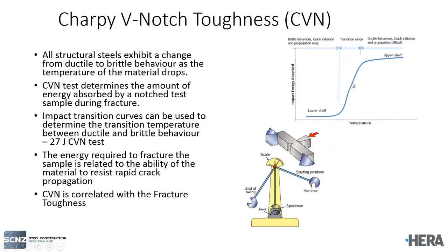The transition temperature is taken as the transition point between ductile behaviour of the steel and brittle behaviour, and it's typically defined as the temperature at which, if you were to test the sample, you would have 27 joules of energy absorbed. So above that transition point, it takes quite a bit of energy to break the sample. Once you get below that transition point, you require very little energy to break the test sample. So the energy required to fracture the sample is related to the ability of the material to resist rapid crack propagation or brittle fracture. And there are correlations that you can make between the Charpy impact energy and the fracture toughness of the material.